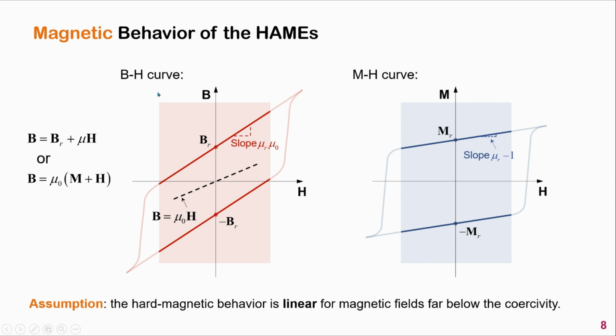Generally, for the hard magnetic materials, the intensity of the actuating magnetic field is relatively small. That means, for simplicity, we can assume that the magnetic behavior is linear. Here, Br is the remnant magnetic induction, Mr is the corresponding remnant magnetization. Mu0 is the permeability of vacuum and mu-r is the relative permeability of the material. Mu-r larger than 1 means that the material will be further magnetized under external magnetic field.